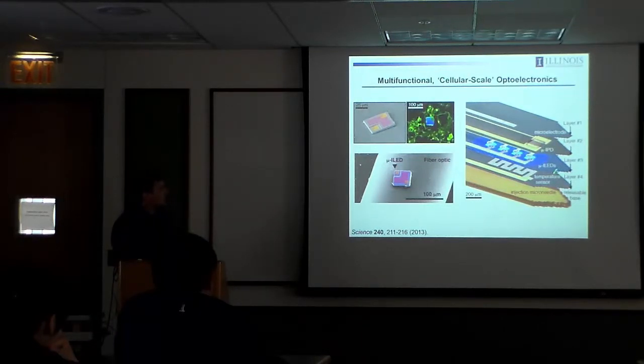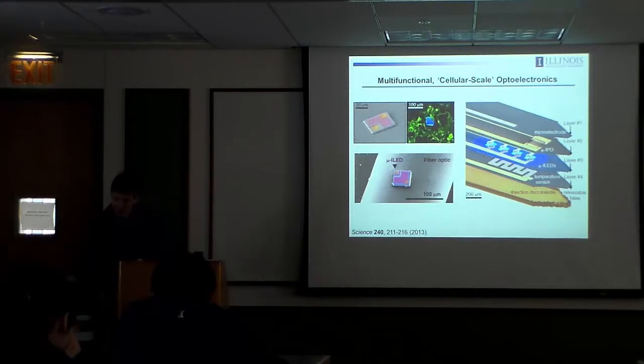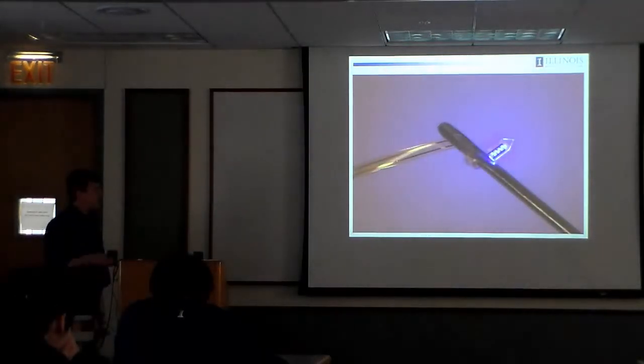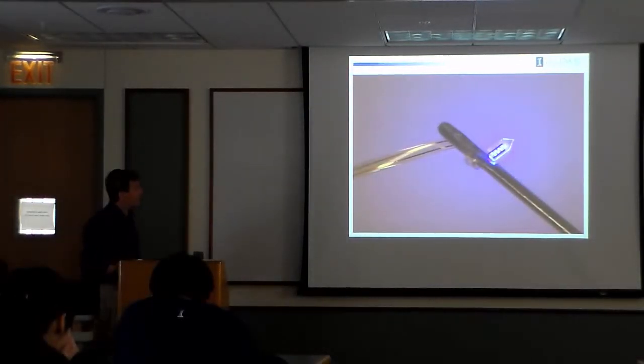So what we do is we use a releasable microneedle that's much thicker, lithographically defined in a polymer to match the shape of these devices, and then adhered to it with a bioresorbable glue. So you inject the whole thing down and then you release the devices by taking the needle out.